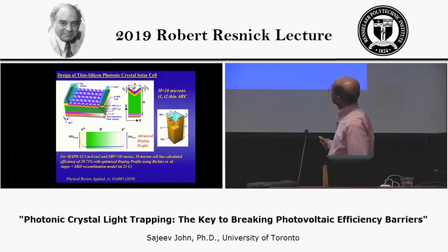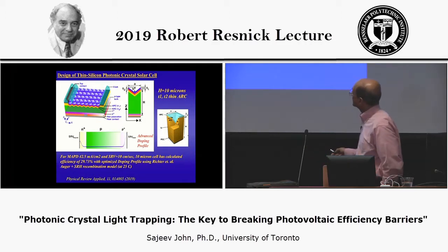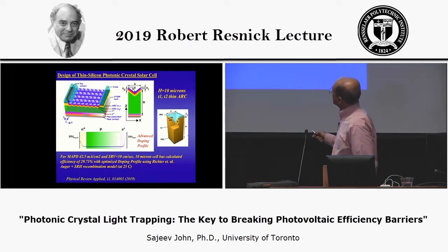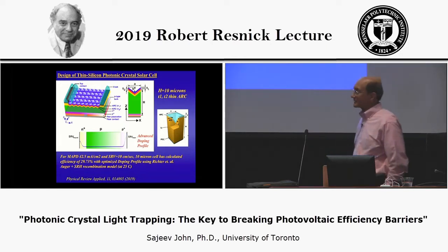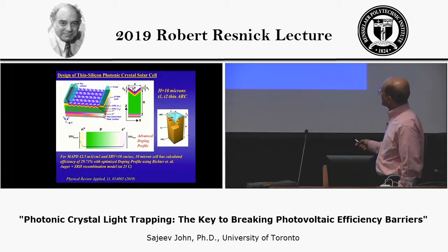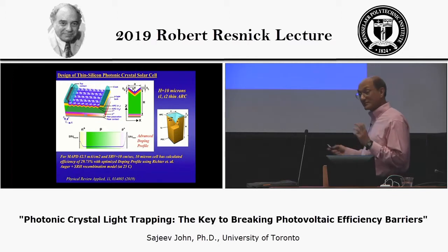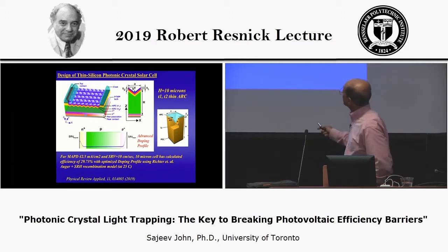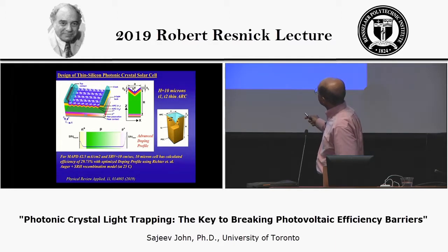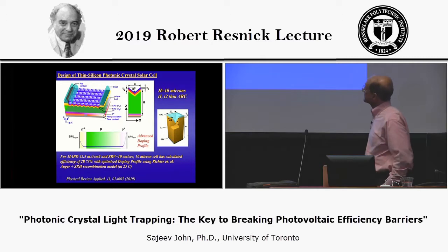So here's an actual design of an inverted pyramid photonic crystal solar cell. We have the pyramids at the top covered by a dual layer anti-reflection coating, and then there's a region with high N doping. So the N doping profile goes up to about 2 times 10^18 per cubic centimeter here. There's a very low doping region, which is P-type, which is about 10^15 per cubic centimeter. We want as much low doping as possible because that reduces the Auger bulk recombination. Then finally, near the bottom, we have a high P-doped region, again separated from the contact with some passivation layer, and the contact comes up and touches the silicon in specified regions.